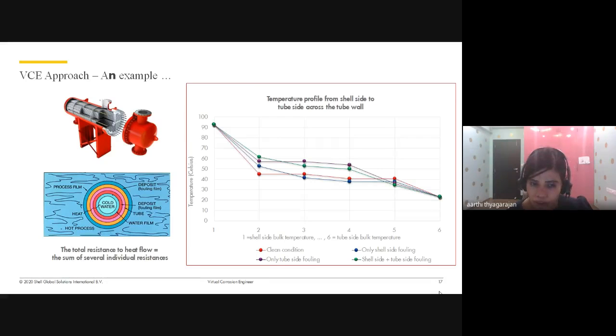Similarly, whether it's based on molybdenum chromium alloy, or is it based on carbon steel alloy, it will determine what will be the limiting values for the tube skin temperature and the velocity. So the expert review of these data also suggested that TST was ranked as the highest risk factor, and so we derived the correlation between the inspection results.